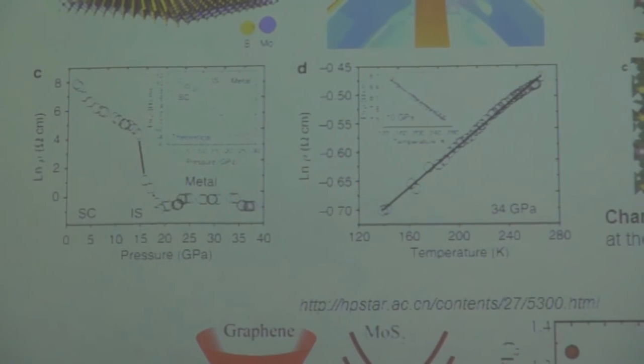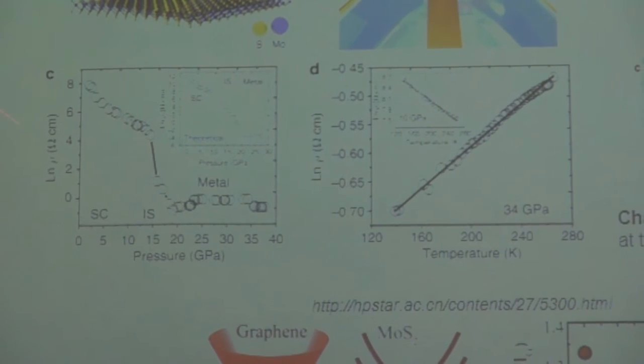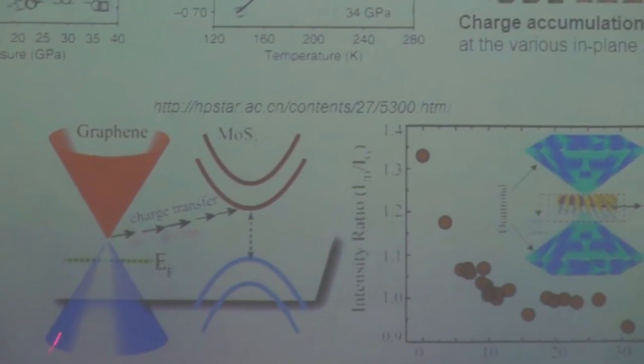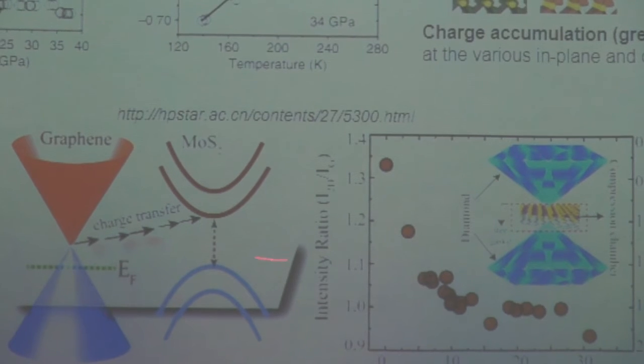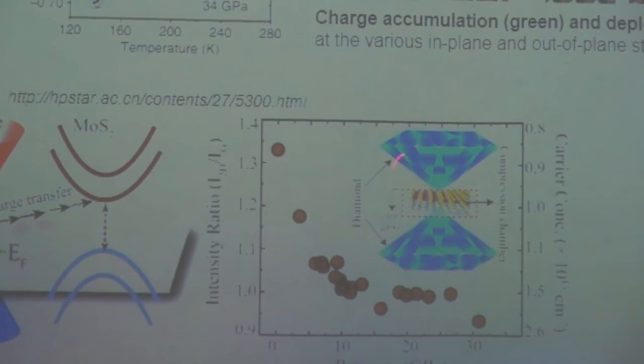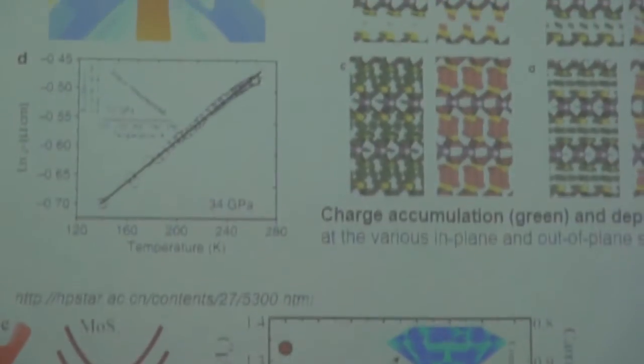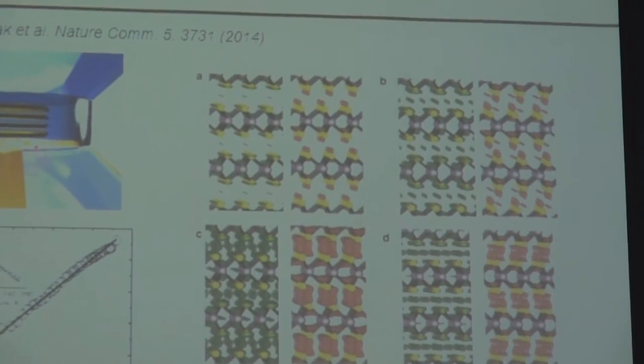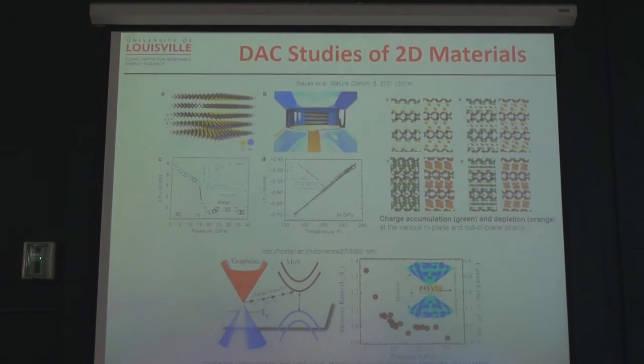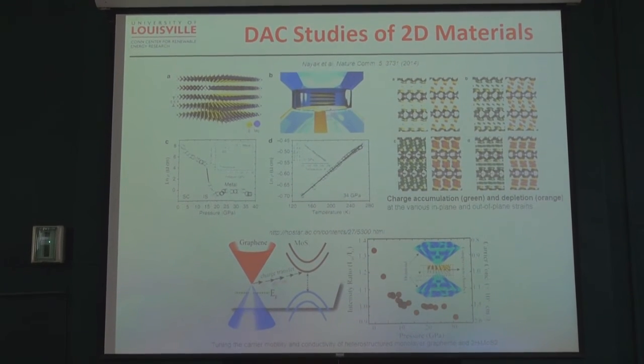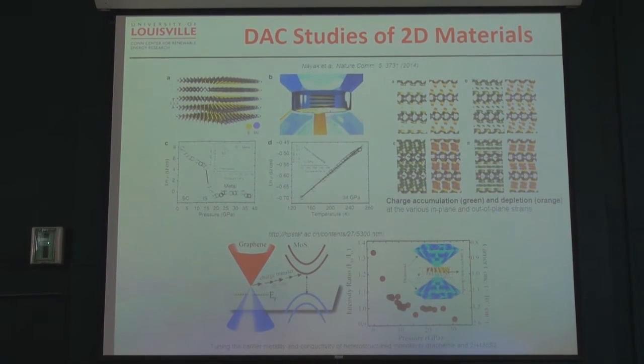What we are planning to do is for phosphorus, but with lithium intercalation. You can see how even graphene or this one goes from metal to semiconductor. Even for some other materials, people have seen phase transitions happening under high pressure. So this is for other 2D materials. You can say the phase transition, right? Like semiconductor to metallic. What we are trying to do is go from black to blue phase transition.